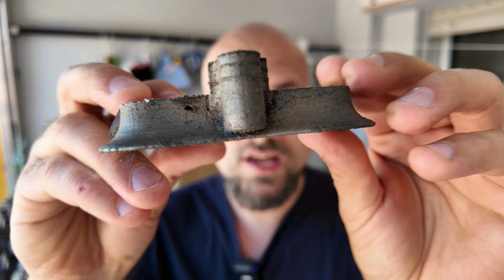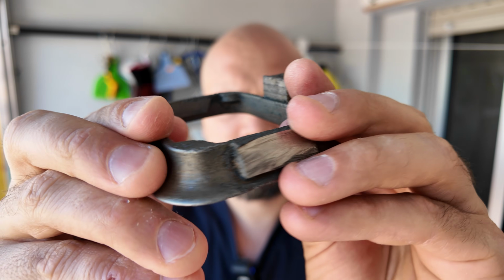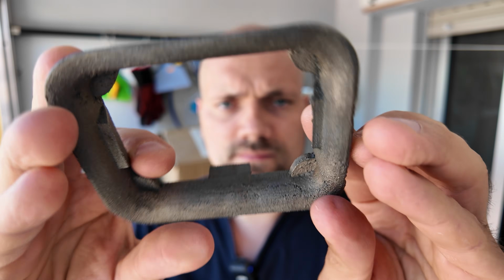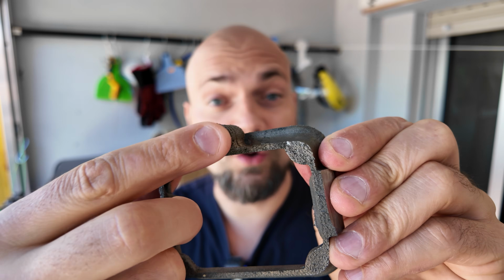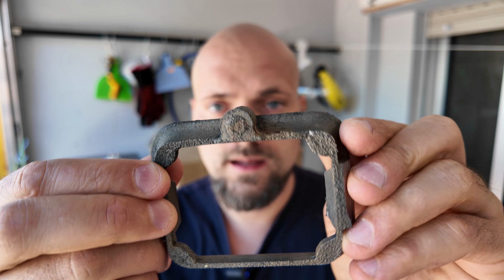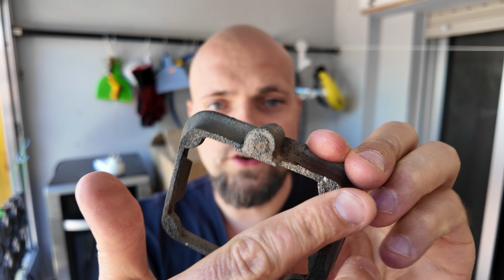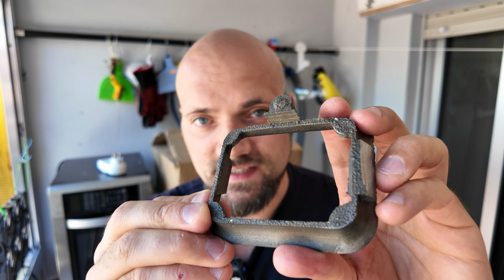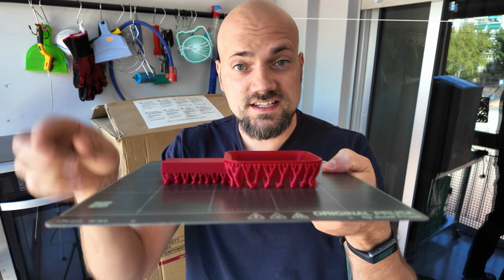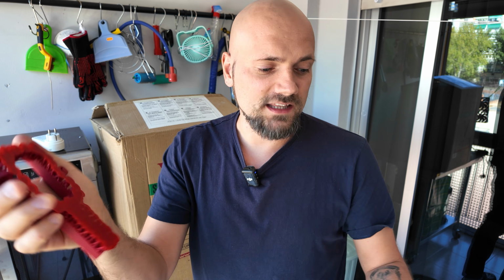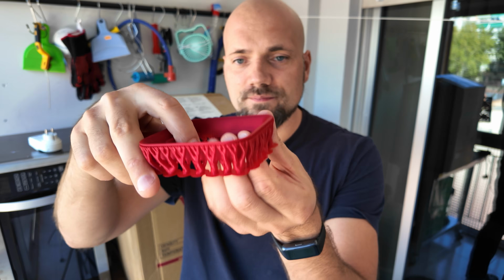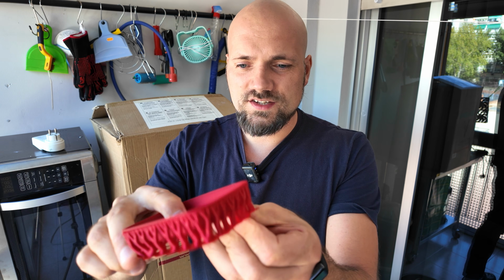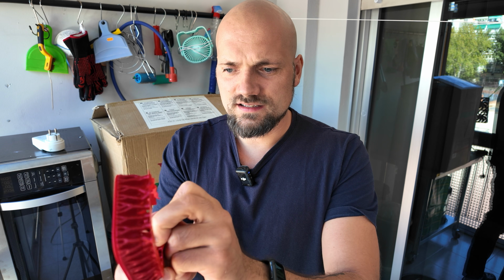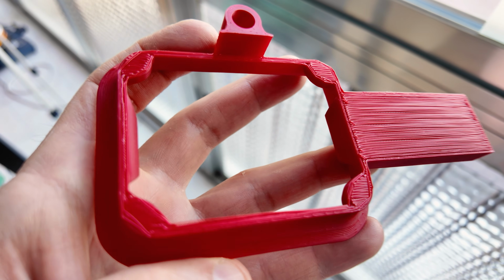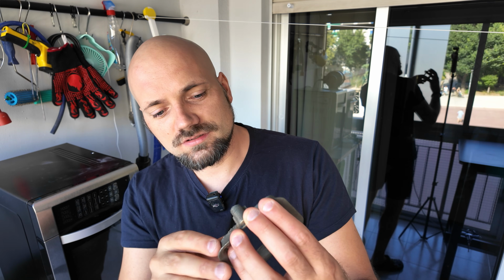There are a few issues with the cast. The biggest one, that there is no hole where it's supposed to be. And the bottom is not very smooth because of the way it was printed. Originally I printed it like this. This is just a draft print, so not the best quality. But just to give you an idea, the supports, once removed, left the bottom scarred. Sure, I could attempt to do it again, but it just didn't feel like the right process.